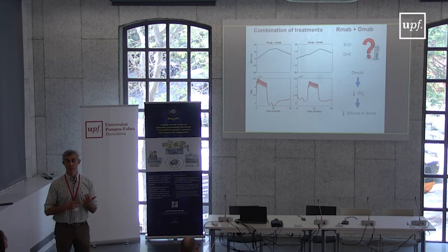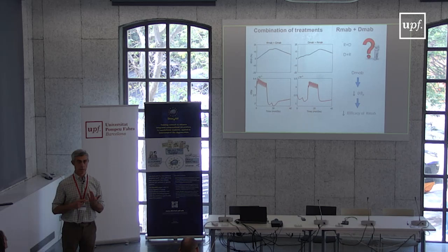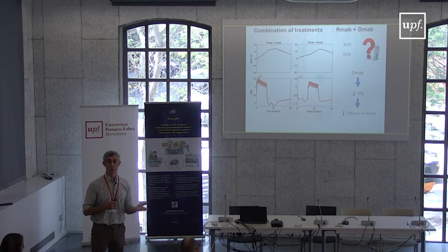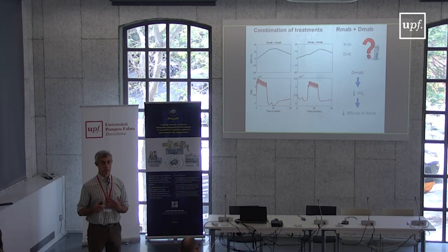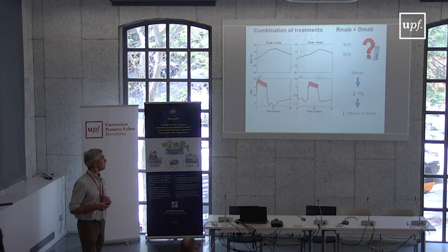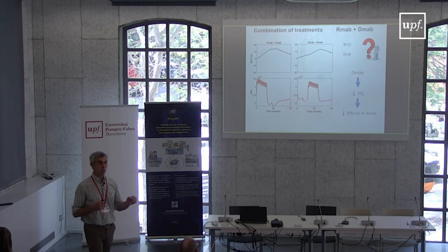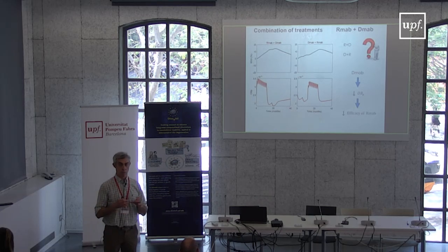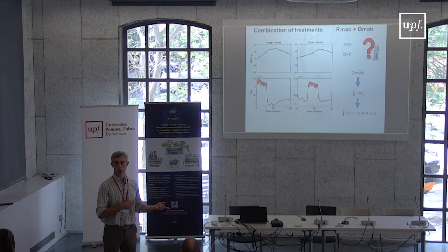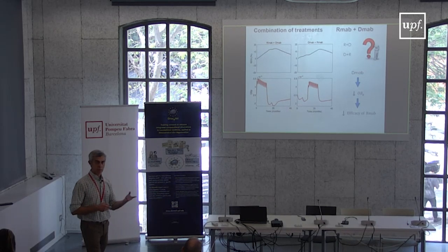Because mineralizing involves fragilization of bone matrix. So you will end up having more microcracks, and your fracture risk will increase. So not a good option in the long term. So why not start with an anabolic where you gain bone volume, and then when you have more bone volume, then you mineralize it. That's what you get with the other combination. First an anabolic and then an anticatabolic. But think of another thing.